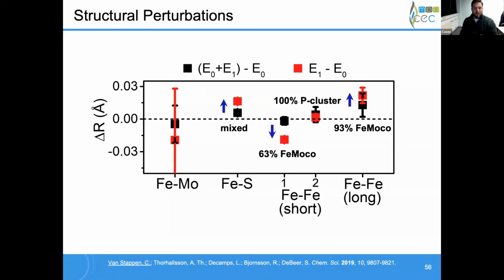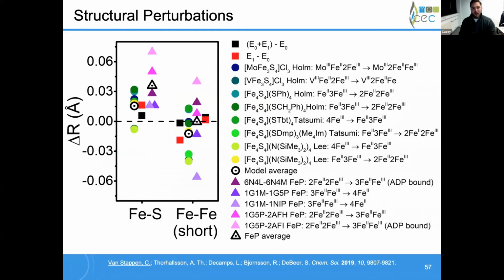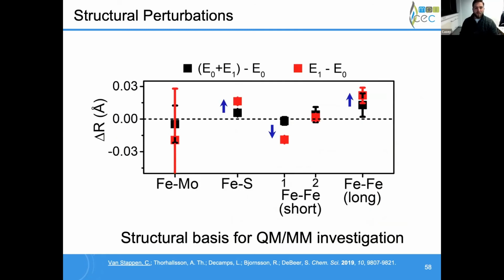It stays a constant all ferrous state. It cycles through one electron oxidized in an all ferrous state, but the population that we actually see is the all ferrous. So this is interesting in its own respect. We can compare that to model complexes for crystal structures, a whole wide range of them. And we find that this increase in iron sulfur distance with a decrease in iron-iron distance is pretty diagnostic for single electron changes in iron sulfur clusters, as well as in the iron protein itself.